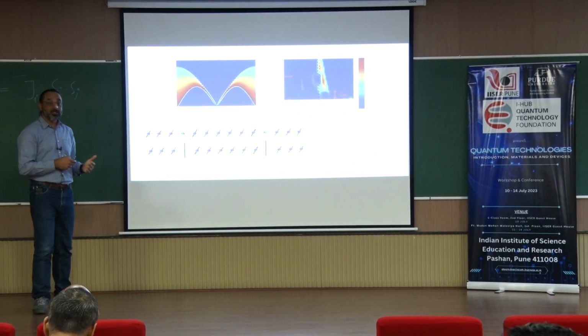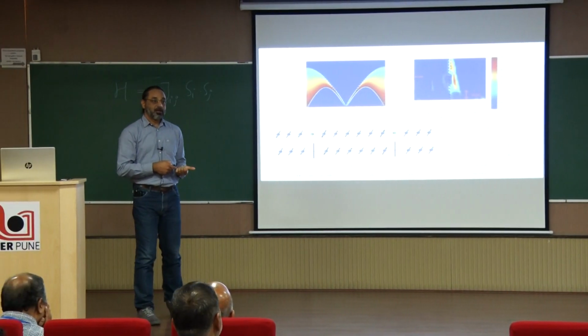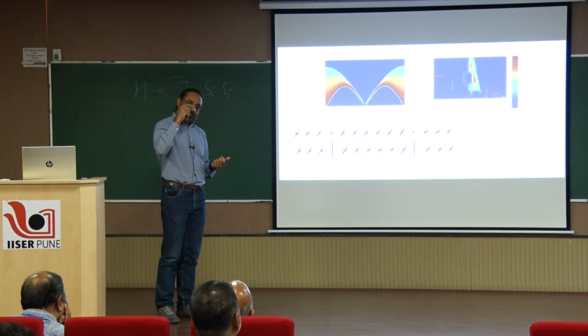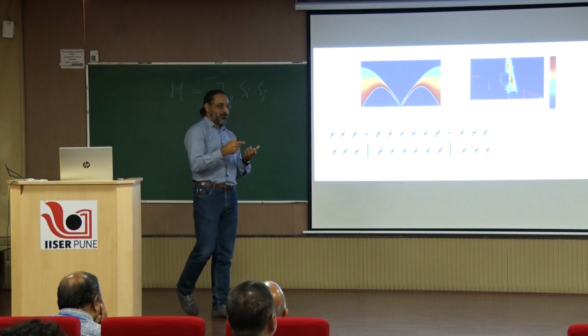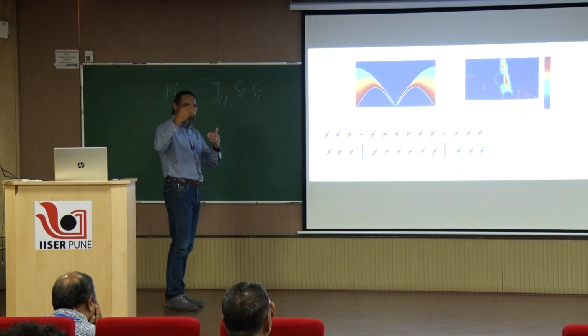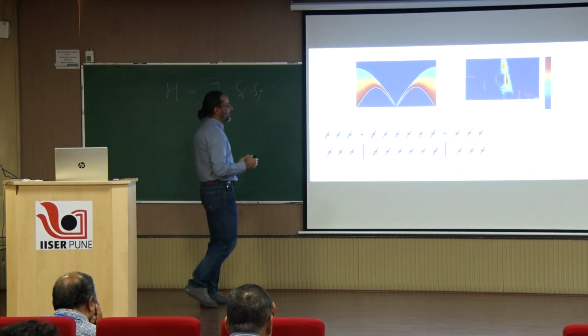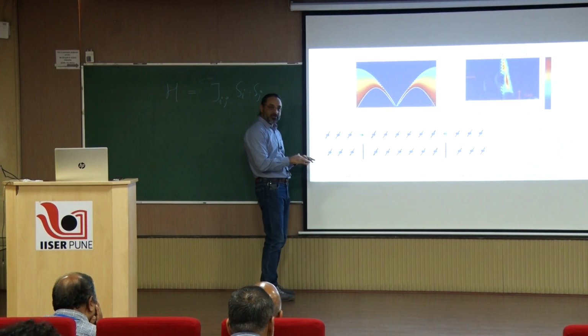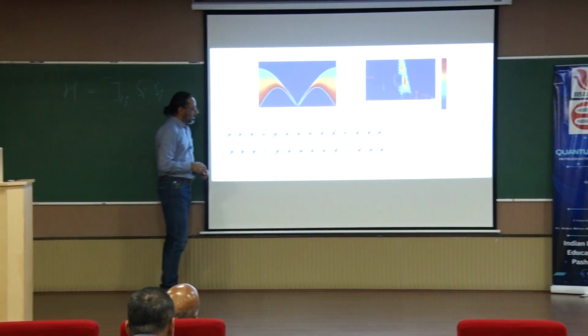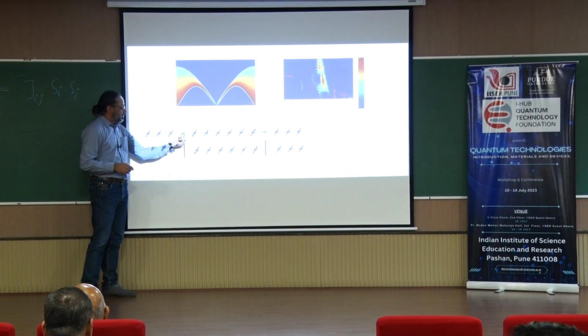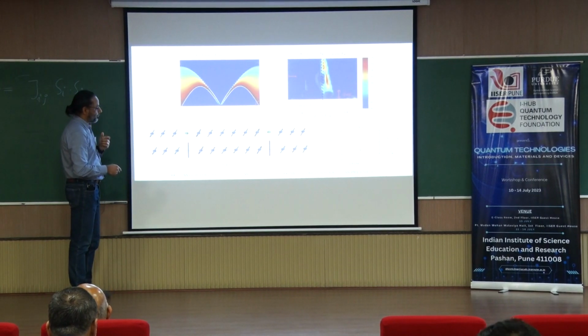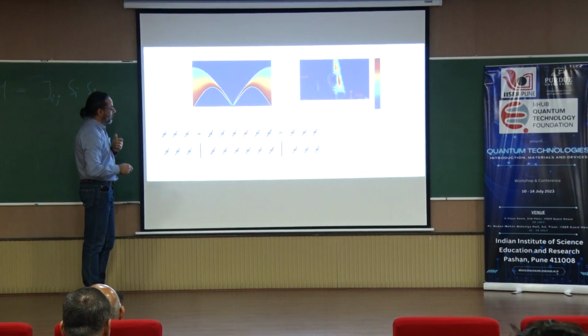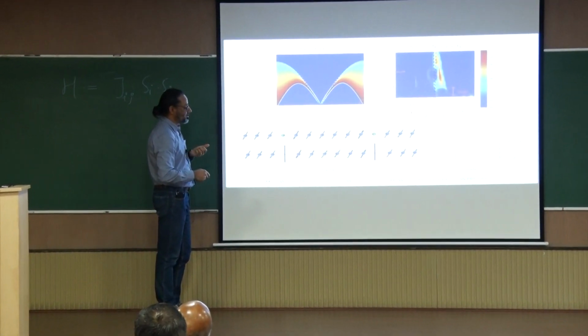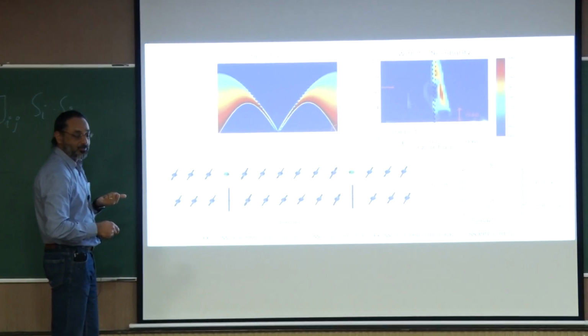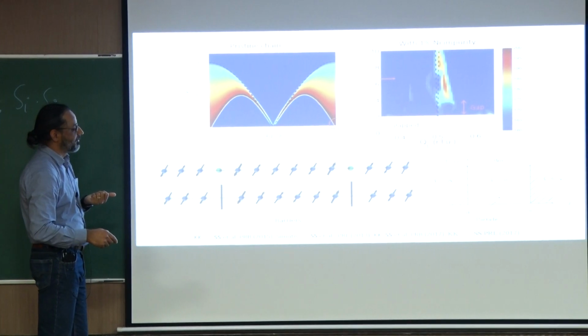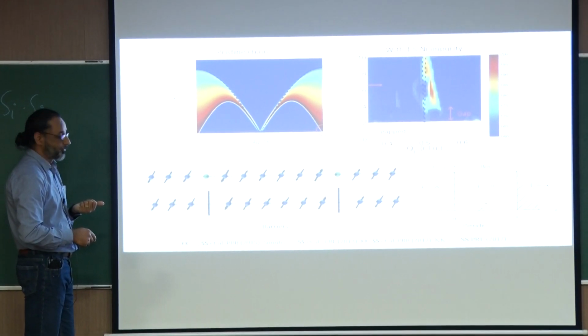You can replace it with nickel. Nickel 2+ is d8. In its low spin state, there are no unpaired electrons. Nickel has two spin states, low spin and high spin, and apparently in this system the nickel has the low spin state. So you can replace it with nickel, and then you create a point in the lattice where the translational invariance is locally broken, right? Because the invariance that was there previously is locally broken here.